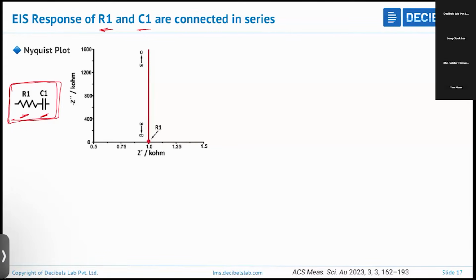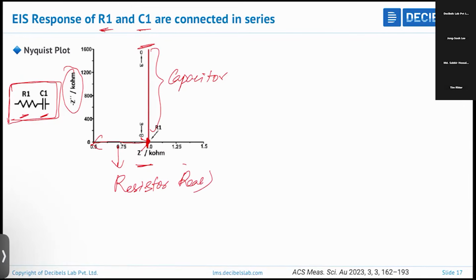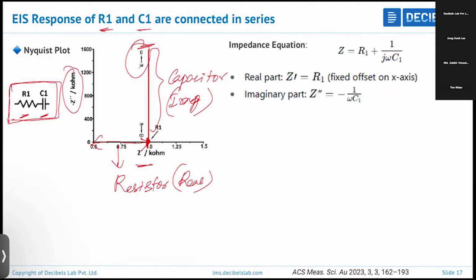So in that case, the Nyquist plot, minus Z double prime versus Z prime, you will get a parallel line, but not along the axis. It is somewhere after some 1 kilo ohm. It means that it has both the components. So this corresponds to the resistor, and this corresponds to the capacitor. This is along the real axis, and this is along the imaginary axis. You can see that the impedance corresponding to the capacitor decreases with increase in the frequency, because it's inversely proportional. This is how you get the Nyquist plot.